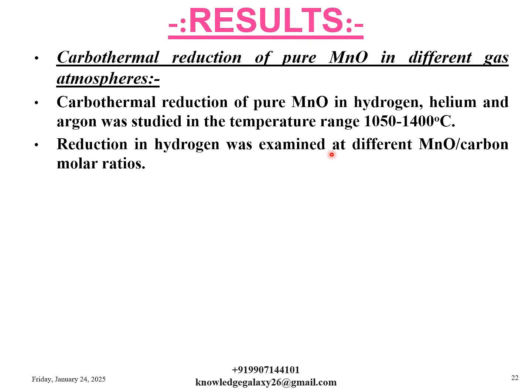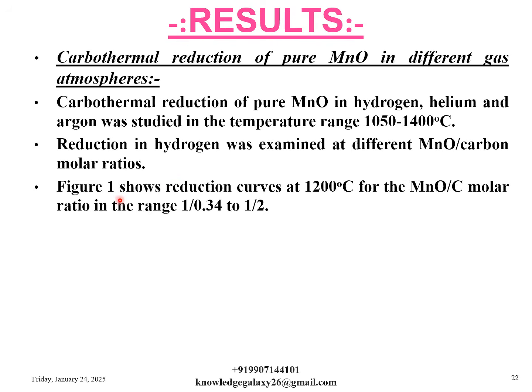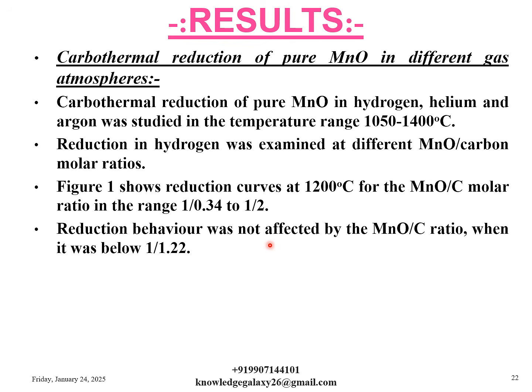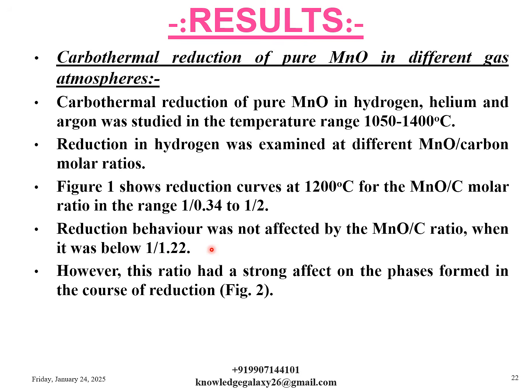Reduction in hydrogen was examined at different MnO by carbon molar ratios. Figure 1, which is presented in the next slide, shows reduction curves at 1200 degrees Celsius for the MnO by C molar ratios in the range of 1 by 0.34 to 1 by 2. Reduction behavior was not affected by the MnO by C ratio when it was below 1 by 1.22. However, this ratio had a strong effect on the phases formed in the course of reduction, which is shown in figure 2.